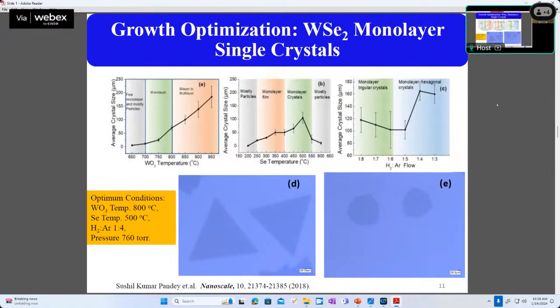Now, a few results which we can see here, like my group did this temperature variation of WO3 with average crystal size. So we found that it increases with temperature. Then selenium temperature, we varied after varying WO3 temperature. We have seen an increment in crystal size, and then it reduces. And similarly, hydrogen and argon gas flow was varied. So finally, we got some material which is single crystal in nature, and that is triangular in shape as shown in figure D and figure E. So you can see very light colored things present here on top of this substrate. So this is basically the material which we get after performing this growth.